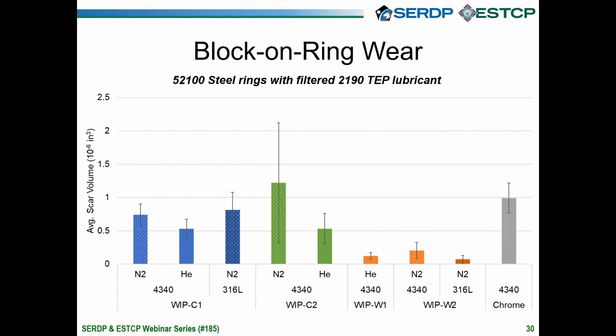We did a variety of different types of wear testing, and this is just one example of wear testing that we did. So this is a block-on ring wear test where we had 52-100 steel rings that rubbed up against cold spray coated blocks and a filtered 2190 TEP lubricant. We did that test for all the cold spray coatings and also a chrome plated sample so we could have a direct comparison. What we found is that all of the coatings except one had better wear performance than chrome plating. The one coating that didn't was the WIP C2 sprayed with nitrogen.